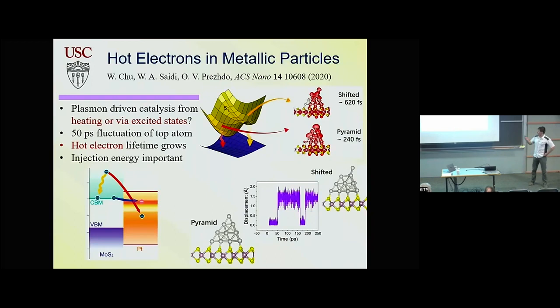So in the simulation, it comes back pretty fast, but also experimentally, it goes back very fast. In the resonant case, when you have this resonance, which is needed for the PICT, what we saw is that you have the back transfer for the relaxed electron. You have like 100 to 200 femtoseconds to extract that electron from the semiconductor side to harvest this. Because this is nice: you can absorb into the plasmon in the near IR and still get an electron out somehow. You have to have some bias so that it moves in the opposite direction, away from it, and do it fast. Yeah, do it fast.